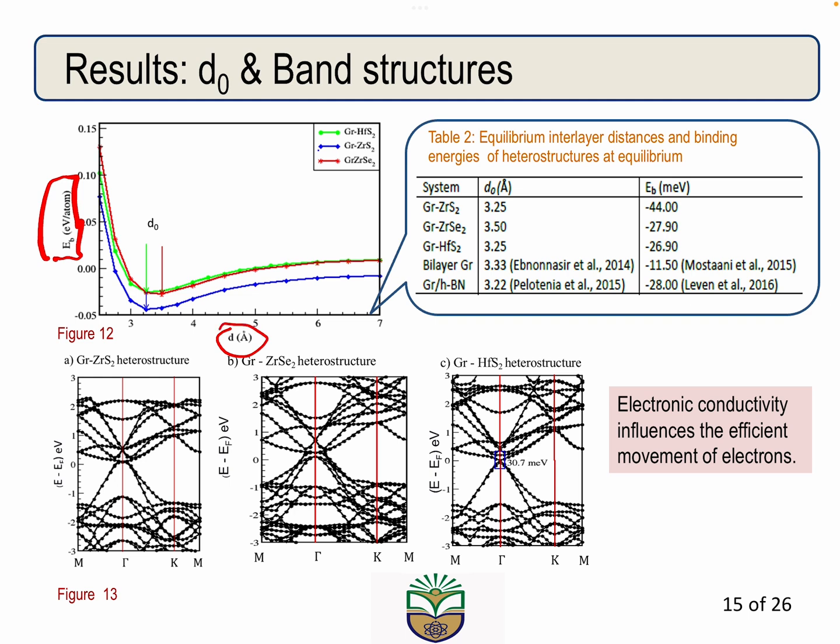And when we did this, we obtained a graph that can be seen to have a Lennard-Jones potential type, which signifies the presence of van der Waals interactions in our systems. So the indicated points refer to the optimal points of the interlayer distance, and these are considered to be the most stable points because that is where we found the curve to have the lowest energy.